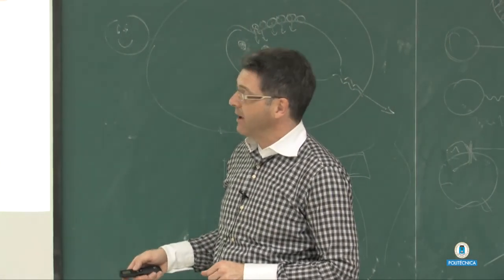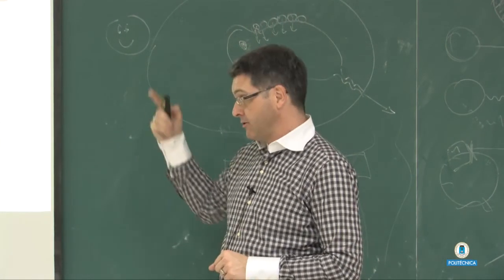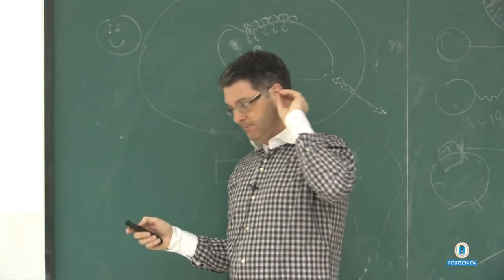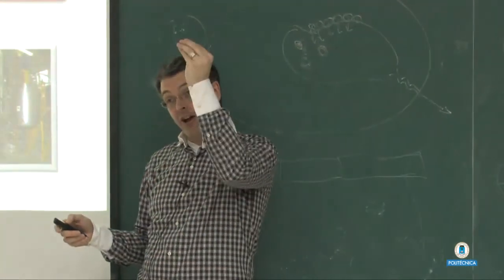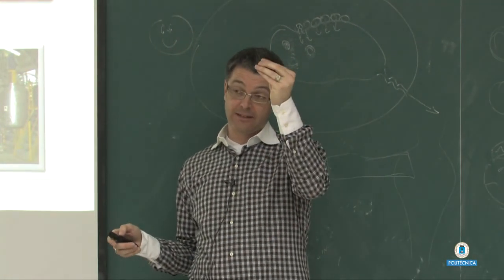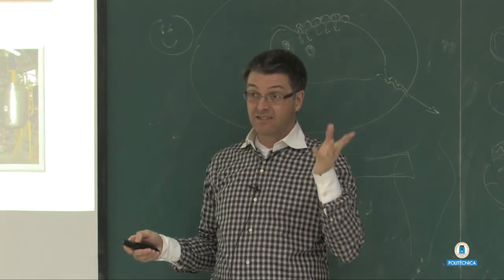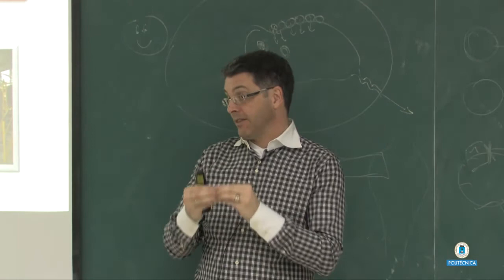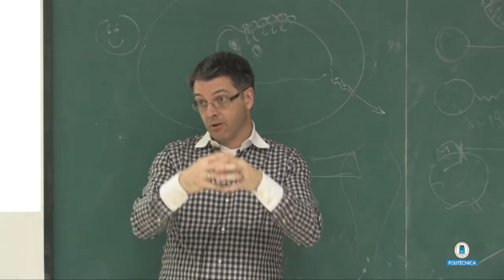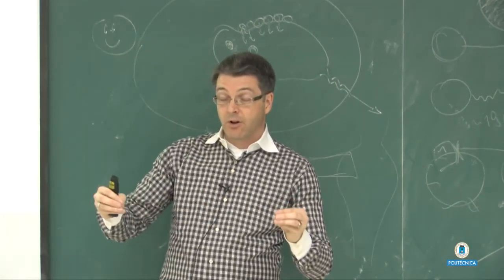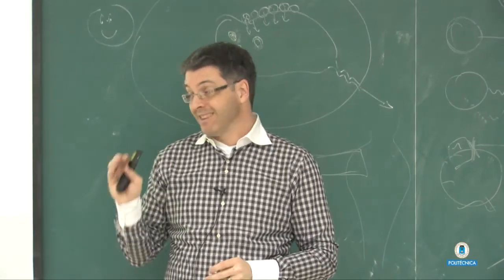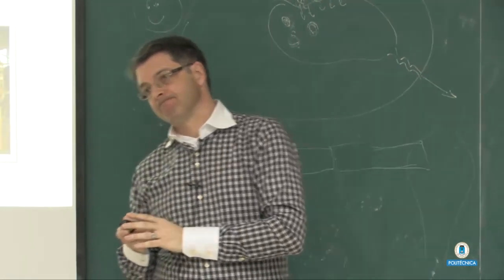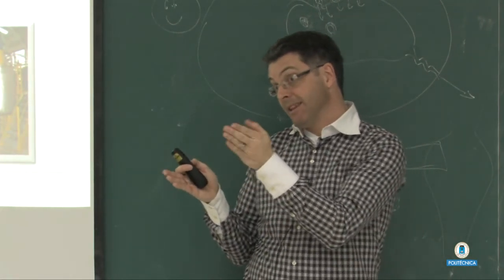I mean, this is one of the major issues we will see next, tomorrow, in the next lecture, when I talk about making fibers. Because you can only make fibers if you have highly concentrated solutions. We talk about 20% weight per volume. And this is only possible with these molecules because they're so soluble that you can keep them in the spinning dope for quite a long time, and they will not fall out, they will not aggregate, and so on. But this is a feature of the sequence, of the primary structure. But you're right, it's a big problem.